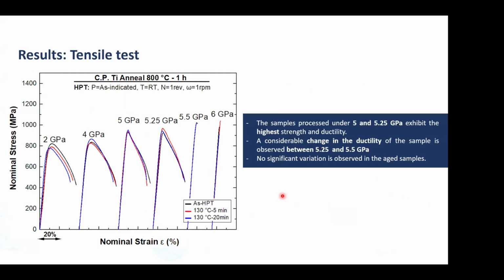But one of the most interesting results here is where we lose the ductility, which is the other important aspect of the equation. We see that somewhere between 5.25 and 5.5 gigapascals, we lose the ductility a little bit abruptly. This is something very interesting, and we are very interested in further investigating it with deeper microstructural analysis than the ones that we are capable of doing here in Costa Rica.